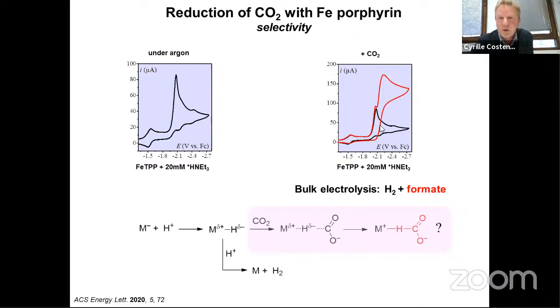And now in the presence of CO2, you observe a second wave that corresponds to a reduction of CO2. And if you run the bulk electrolysis, indeed you observe hydrogen, but also formate. So here was the idea that I just mentioned previously. In this situation, you make iron 2 hydride that will accumulate in the diffusion reaction layer. And then this can react with acid to make hydrogen, or with CO2 to make formate. And because you have consumed all the acid very efficiently at the beginning of the CV, then you just have iron 2 hydride that will react with CO2 to make formate.